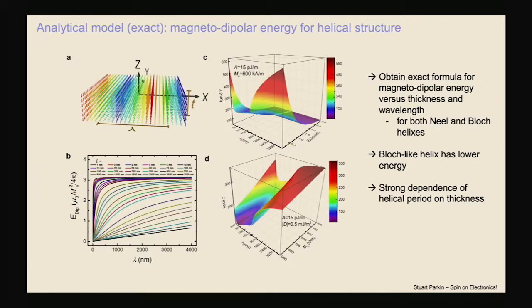And of course, we can calculate what is the reason for this. And the reason, it turns out, is completely due to dipole energy, long-range dipole fields that in these thin layers cause suppression, cause shrinkage of the structures. As we increase the thickness, these dipole fields become less important, and then we actually see the size reflected by the ratio of the Heisenberg to the Dzyaloshinskii-Moriya exchange.